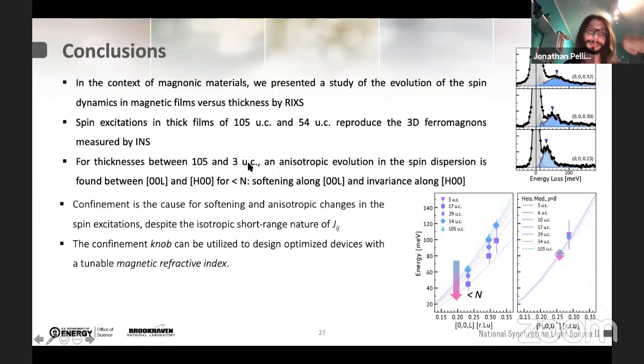And based on this groundwork, we investigated the thickness dependence of magnetic thin films, observing a non-isotropic evolution of the spin excitation along the 00L out-of-plane and H00 in-plane directions. And we observed a softening that can be easily modeled by a pretty simple Heisenberg-like model and can be used also to calibrate additional new materials to tune the spin excitation energy.